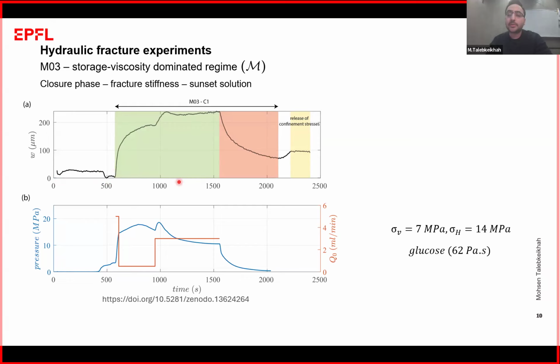So here you can see that the green part is related to the propagation of the fracture until the shut-in time, and after shut-in time, we have a closure phase. And after the experiment, when everything is done and we release the confinement stress, we can see a slight change in the middle of the rock, which is just related to elastic deformation of the rock because of releasing the confinement stress. And the other really interesting thing is that the opening after the full closure never reaches zero. A kind of residual opening remains inside the fracture.